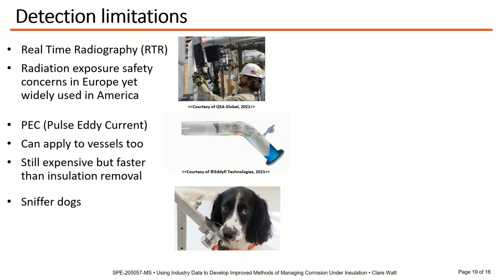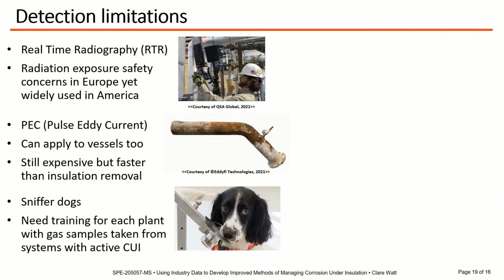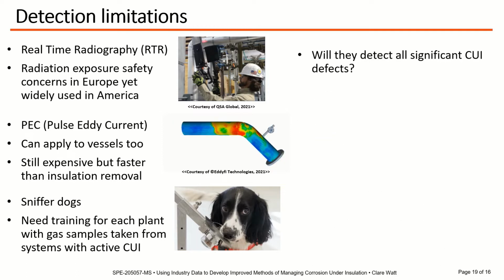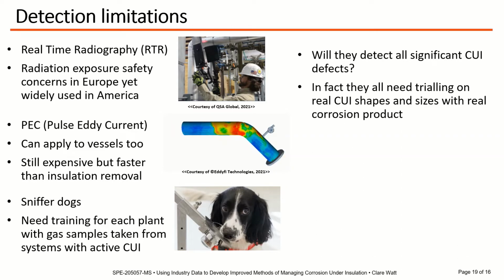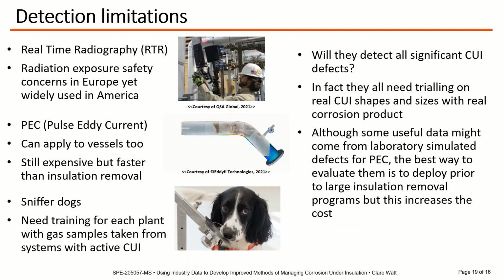Sniffer dog technology, pioneered in Norway, has shown great promise, but there is a need to train the dogs for each plant with gas samples taken from systems with active CUI, which is quite difficult to organise. The big question is, will they detect all significant CUI defects? And in fact, because of the way they work, they all need trialling on real CUI defects and corrosion product. There might be some useful data that can come from laboratory simulated defects, especially for pulse eddy current, but ultimately the best way to evaluate these techniques is to deploy them prior to large insulation removal programs, although this increases the cost of an already expensive exercise.